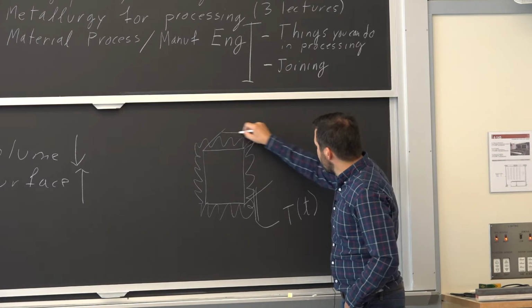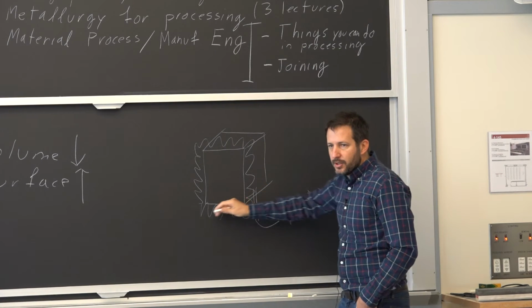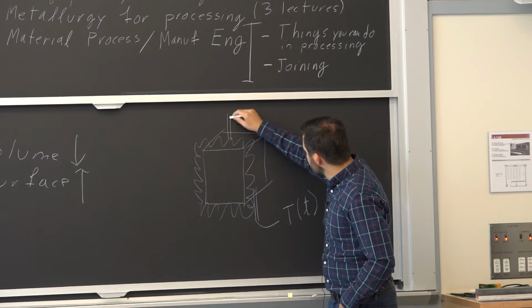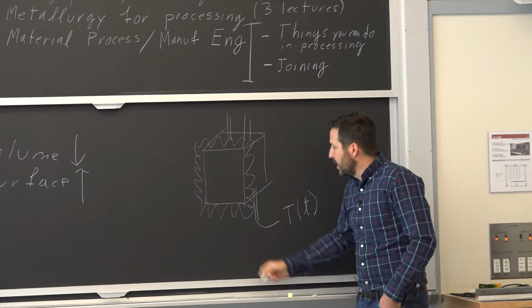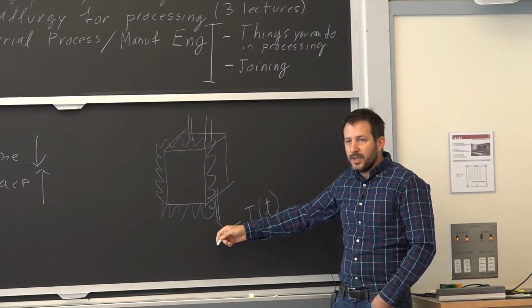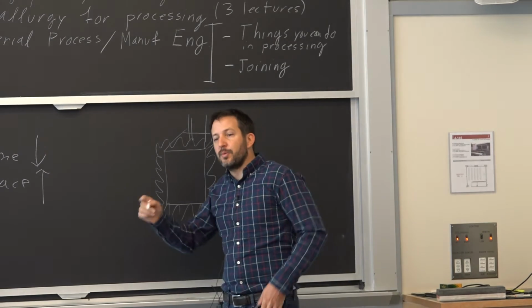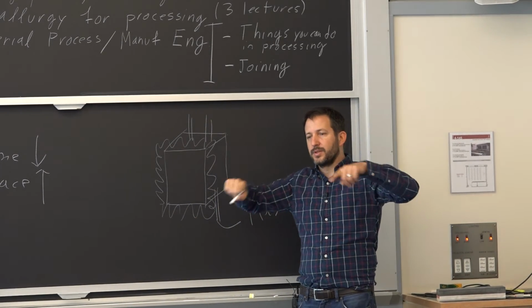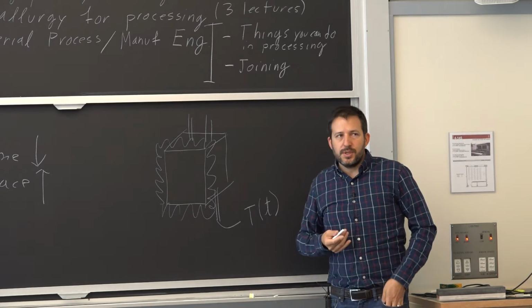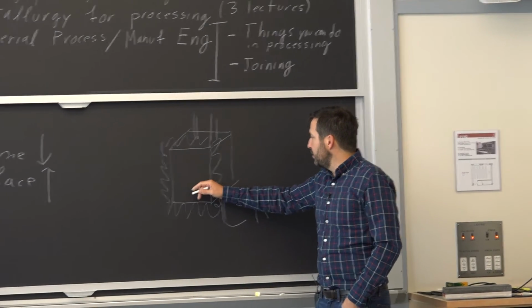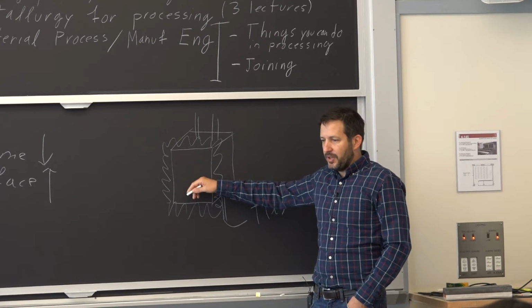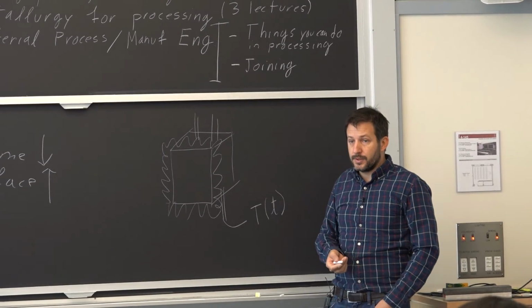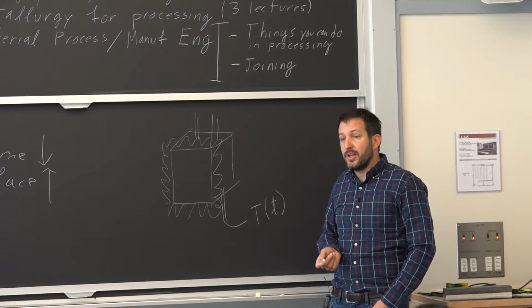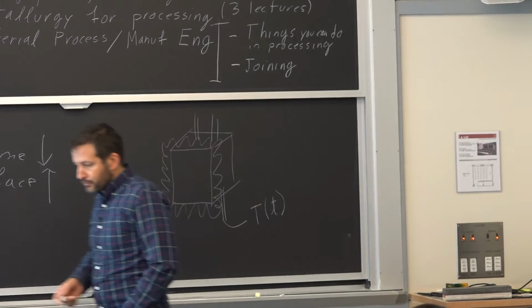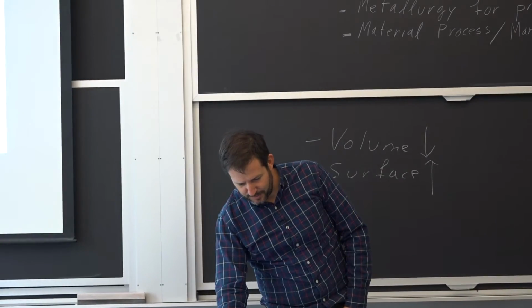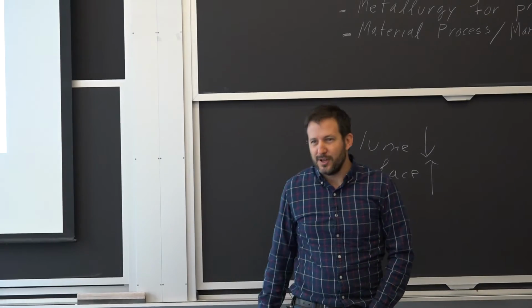So let's say you get that box. It's all insulated all around. It's got a cooling system to it. Then it has a surface. You lower it into the melt. And it's very close to that strip caster that we talked about with the two wheels coming down. So the purpose of the experiment was specifically to look at what happens with different conditions of the roll surface in this nucleation process.